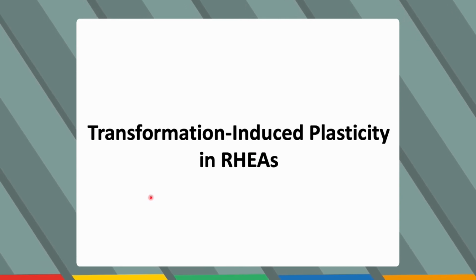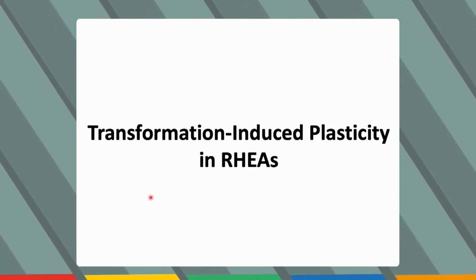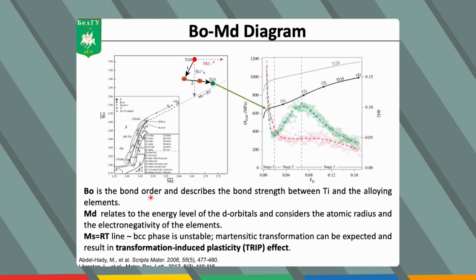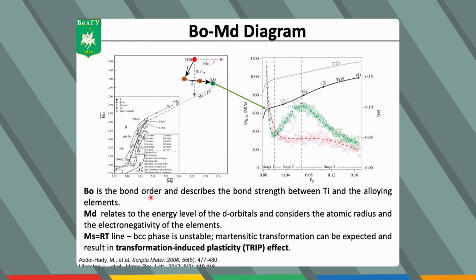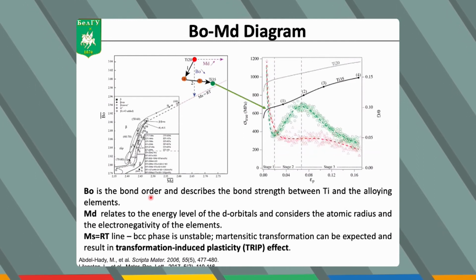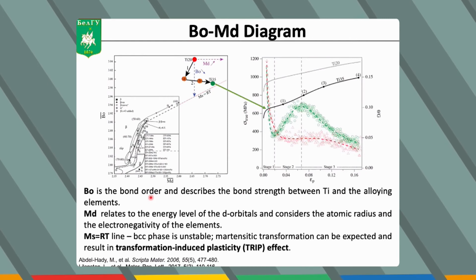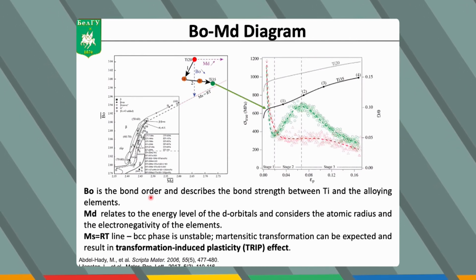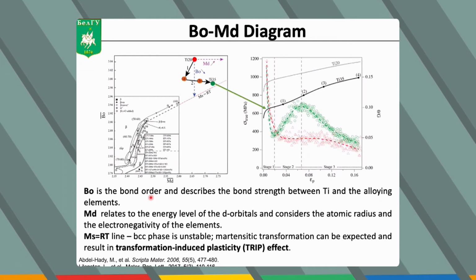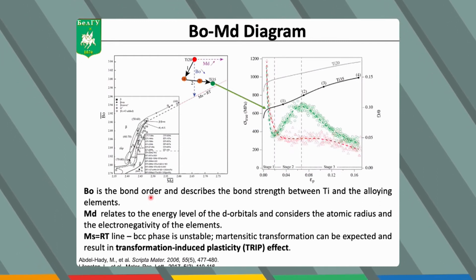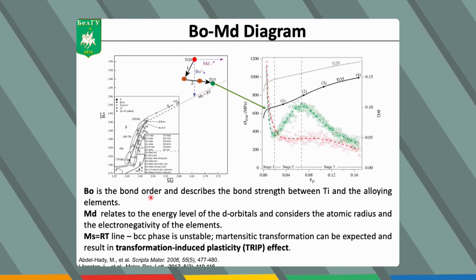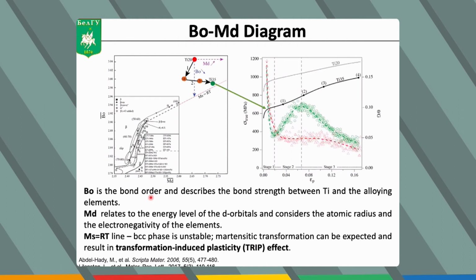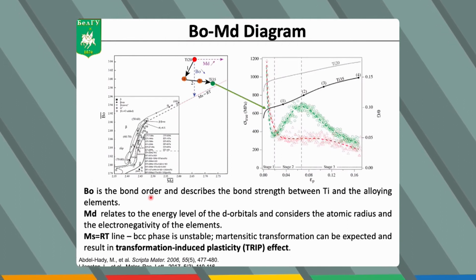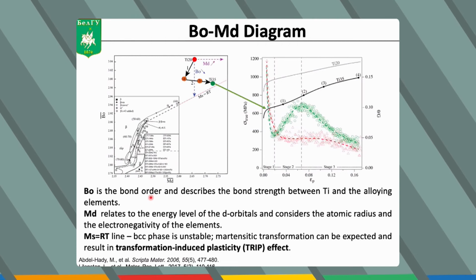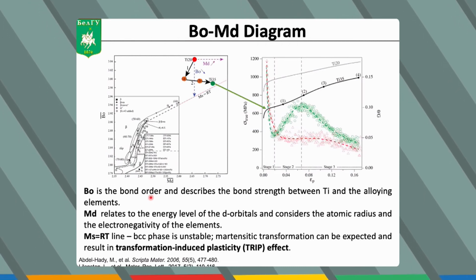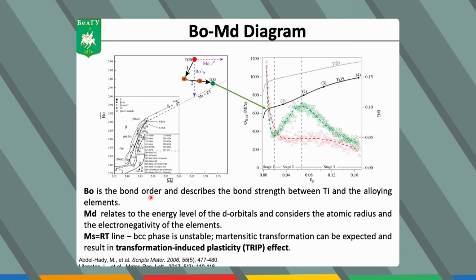And first, let me talk about the transformation-induced plasticity in refractory high-entropy alloys. So it is well known that in metallic alloys, the ductility can be considerably improved when some special deformation mechanisms are activated. And one of the examples of such deformation mechanism is the martensitic transformation. It can considerably increase the strength, ductility and strain hardening in the metallic alloys, and this effect is called transformation-induced plasticity or simply TRIP effect.